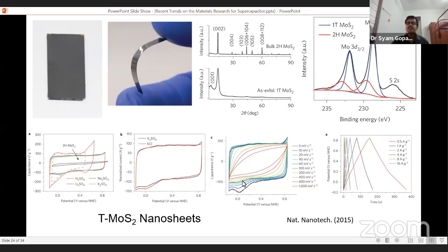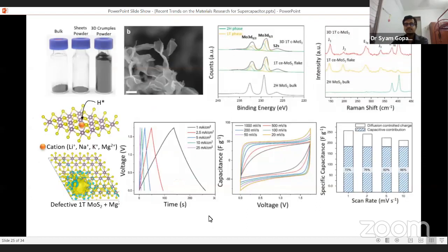But we can take the instantaneous capacitance at each instant, so that the average capacitance can be calculated from this instantaneous capacitance, and it comes in the category of pseudo-capacitor. This was an interesting work of synthesizing metallic 1T-MoS2 from this 2H-MoS2 by the selective etching method.